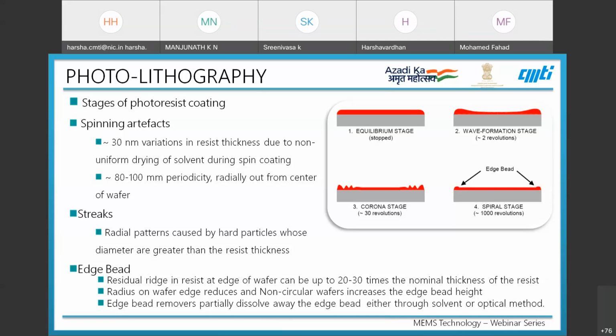Then the residual ridge, as seen in the spiral stage at the edge of the wafer, can be at times up to 20 to 30 times the normal thickness of the resist. The radius of the wafer edge will reduce, and non-circular wafers increase the edge bead height.